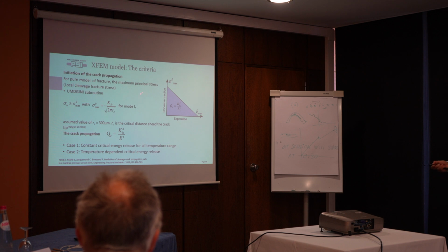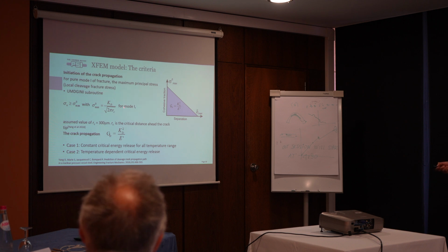We also need for the XFEM model the initiation and propagation criteria. So we consider only pure mode 1, as the maximum principal stress. And in order to make it dependent on the temperature, we relate this using linear fracture mechanics with the fracture toughness that we already know. We need also these parameters. We assume for now 300 microns, but we have to perform the experiments and try to figure out or connect this with the microstructure of the material.